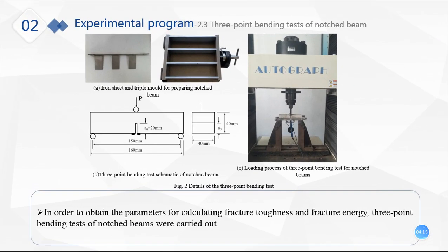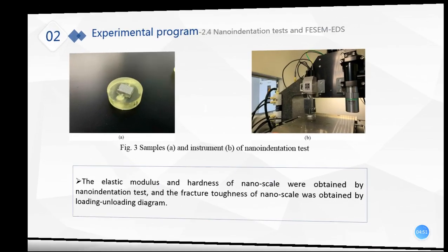In order to obtain the parameters for calculating fracture toughness and fracture energy, 3-point bending tests of notched beams were carried out. This figure is a mold for preparing notched beams, and this figure is the picture of the notched beams, and the right one is the loading process of the 3-point bending test for notched beams.